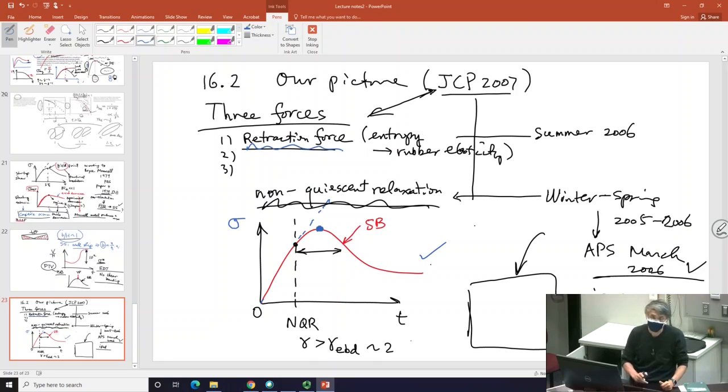Well, we very simply say, oh, you have uncrossability, which we call the entanglement. We carefully discussed that. And that will provide you the effect like a cross-linking so that even though I have millions of layers, I can hold only the end layer and shear or stretch and still be able to enact all the deformations at all chain levels. In other words, at the strand level at least.